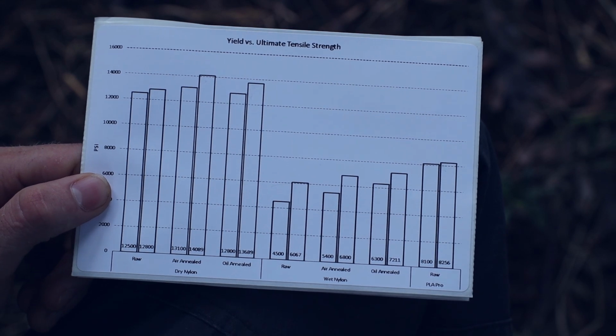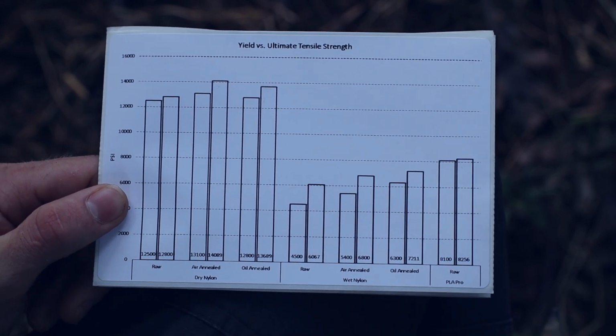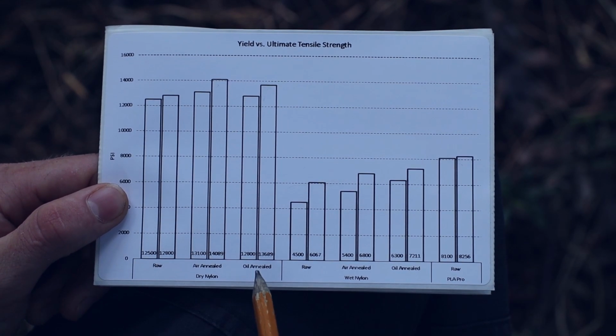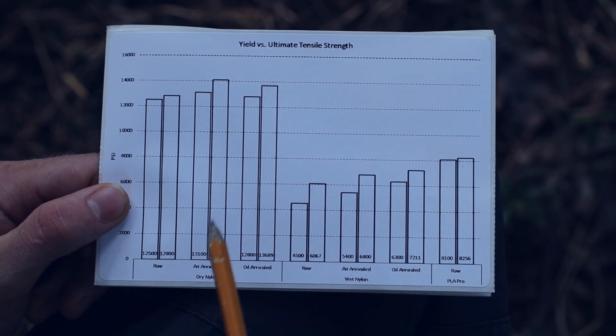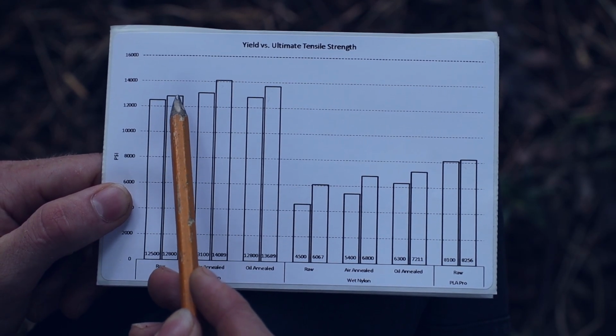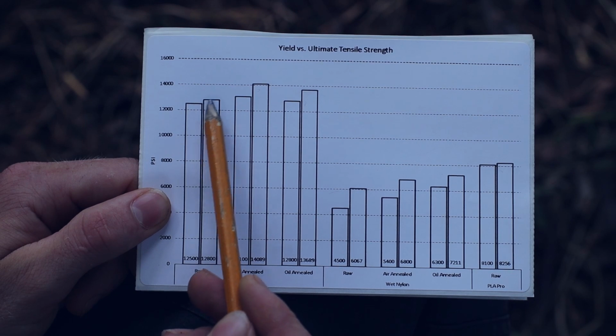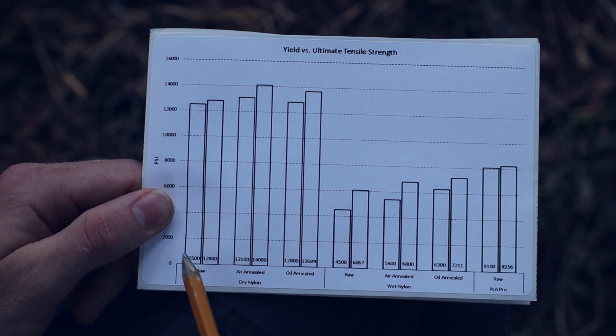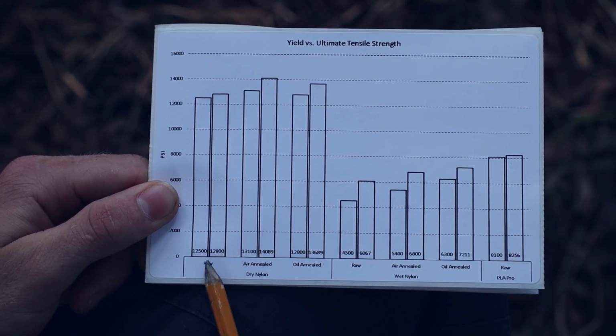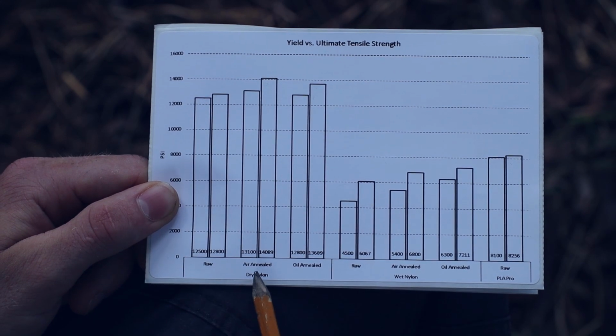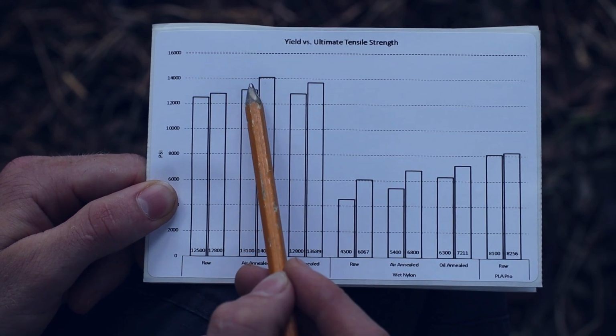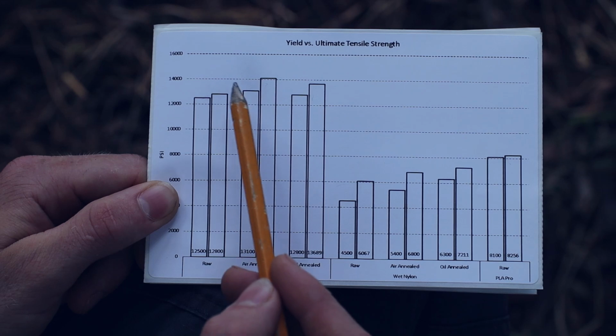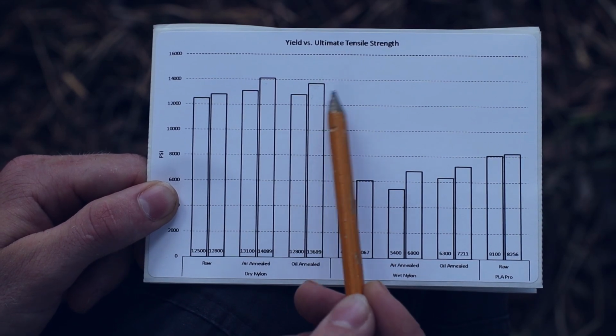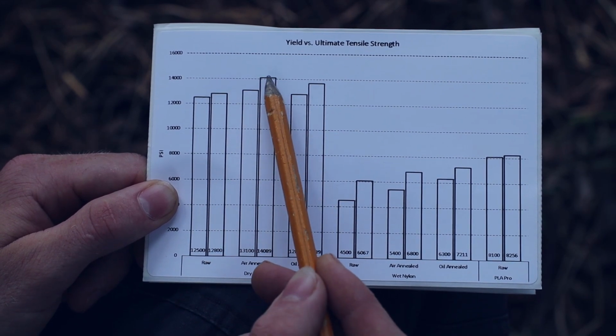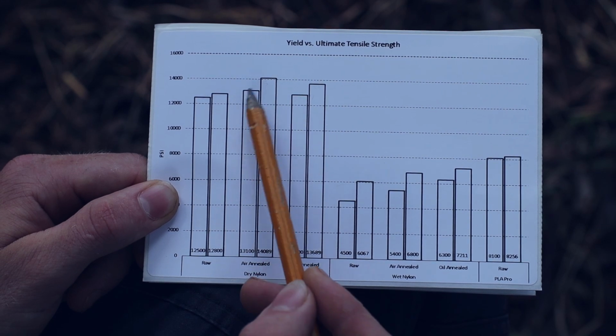I approximately looked at all of these graphs, these stress strain curves, and did the best I could to pull out the yield point. And I've here compared the yield point to the ultimate tensile strength. So with our dry nylons, they're not particularly ductile, and the yield point of the material is not very far behind the ultimate tensile strength. Interestingly, the raw nylon had very little yield at all, and the air annealed and the oil annealed nylons had a bit more yield. And you'll see this when we start looking at the stress strain curves.